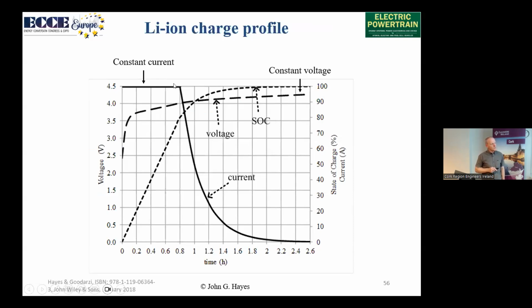And then what we don't want is the voltage applied to the cell to go above about 4.2 volts. So we're going to taper off the current, and we're going to get a slower charge as we put the final charge into the cell. So for this reason, we cannot do high power charge of a battery to 100% state of charge. We typically have to scale back at maybe 80% state of charge and let the onboard charger take over.